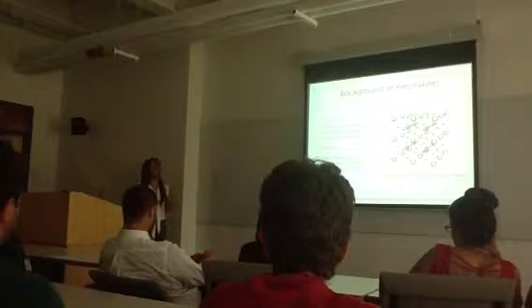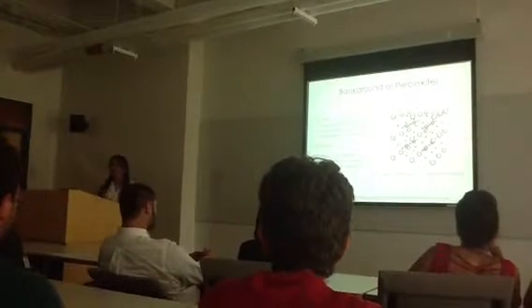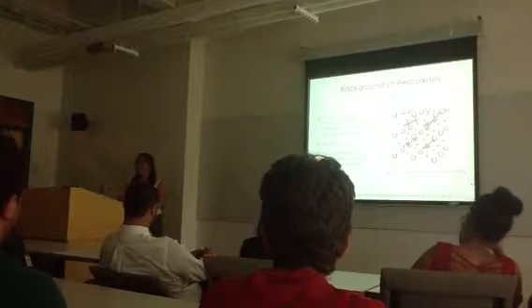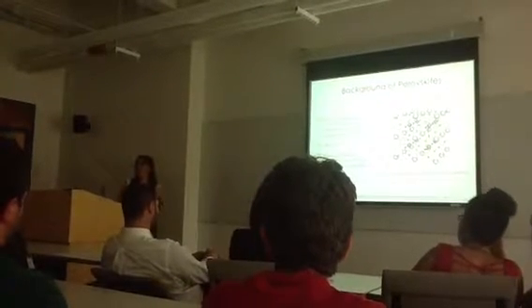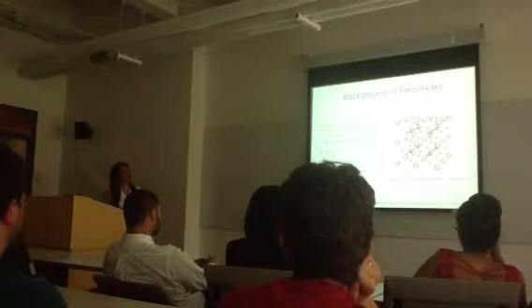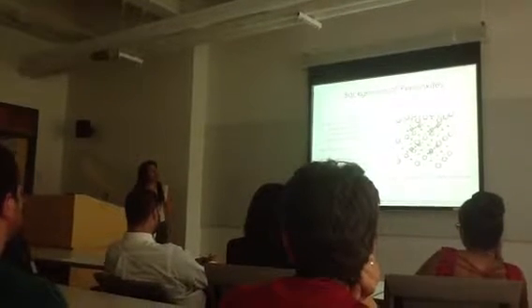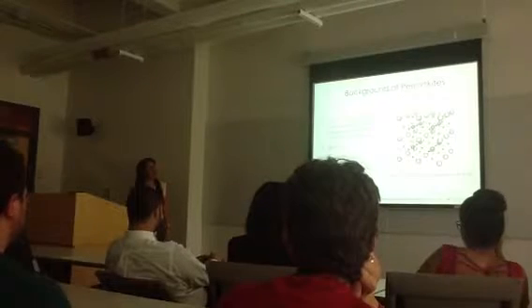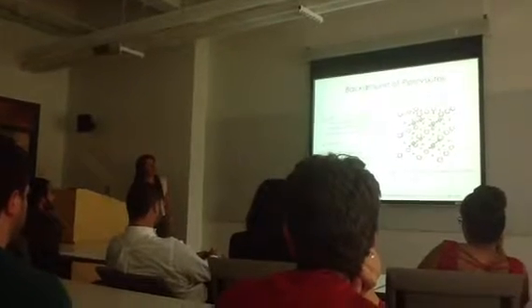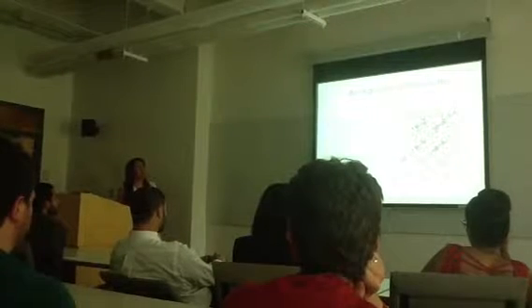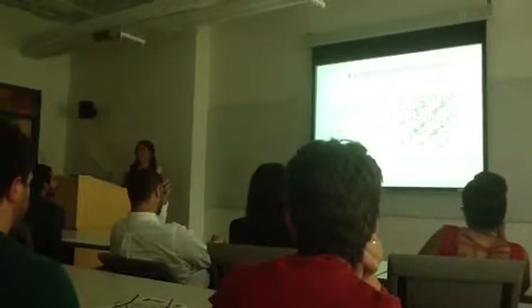So we start from that point, and my lab thought, why don't we use perovskites? Why perovskites? Because previous studies have shown that 90% of the metals from the periodic table maintain their characteristics when synthesized in this type of structure. So this sounds too good for us. This type of structure has the form ABO3, being 2 cations and 1 anion. The A is the biggest one, which here is represented by the green balls, and the B one is the blue balls, in which, for our purposes, we will be changing the ratio of nickel and iron.